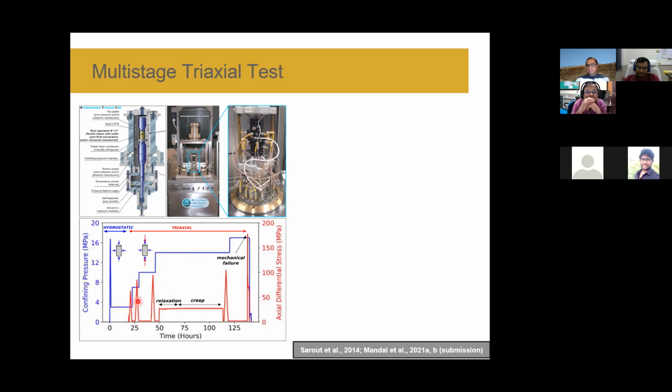and you can see several stages have been done, like loading and unloading. We could do this as a single stage if we have enough sample from each depth interval, but if not, then we can do several stages of loading and unloading cycles. And this loading and unloading was maintained considering that the sample does not reach its fatigue stage or damage stage, utilizing its